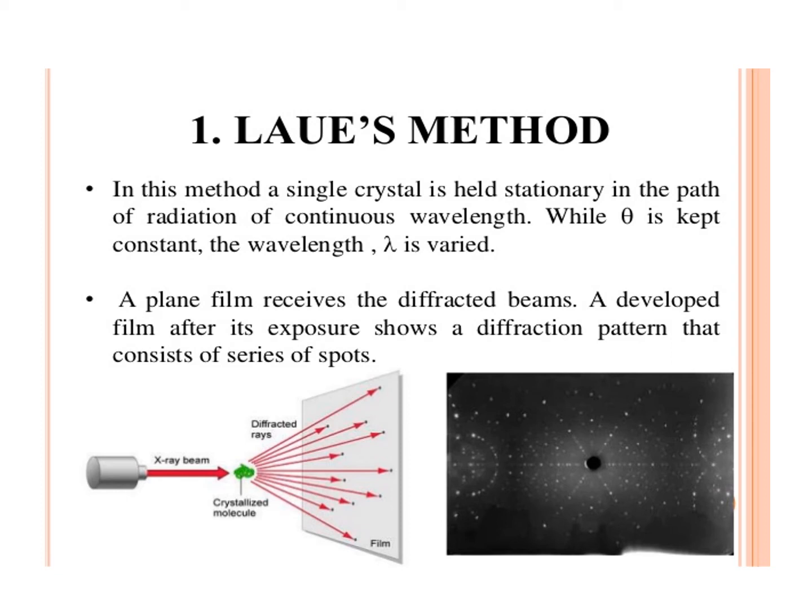Laue's method is able to indicate the symmetry of the crystal. Also, the Laue technique has been extended to the study of imperfections resulting from crystal growth or deformation, because it is found that the Laue spots from perfect crystals are short, while those from deformed crystals are elongated.